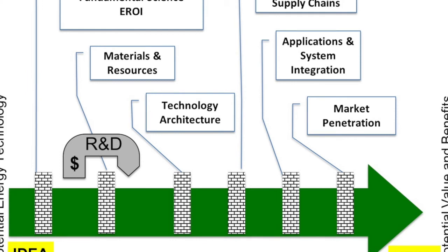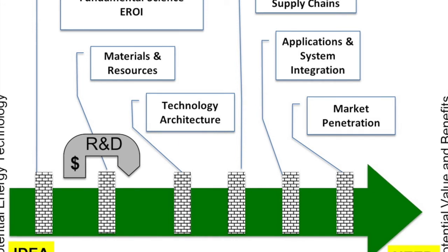When you're looking at a fuel cell like for the Toyota Mirai, again roughly 100 kilowatt, let's round up the numbers. We would be somewhere ranging between 50 to 100 grams of platinum. I give a big scale so that we just have a nice number to play with. It doesn't change the outcome later. Right. But we have this 50 grams, 100 grams. That's for one car.